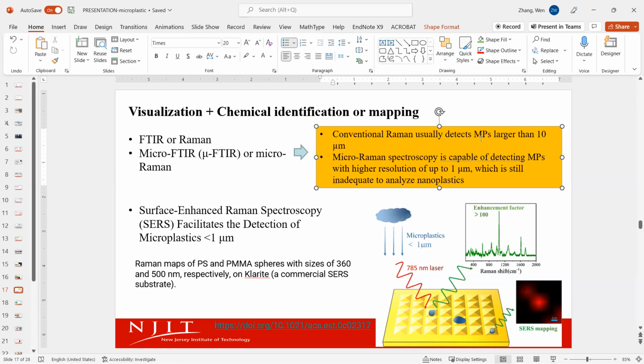This is a huge limit in our opinion, even though it is already small compared to the 5 millimeter plastic fragments, right? But again, in nanoscience, this is too large. There are also emerging techniques called micro-Raman spectrometry or micro-FTIR. Again, the best resolution they can achieve is still not really below 1 micrometer detection limits. So anything below that, we're not going to see very clearly.